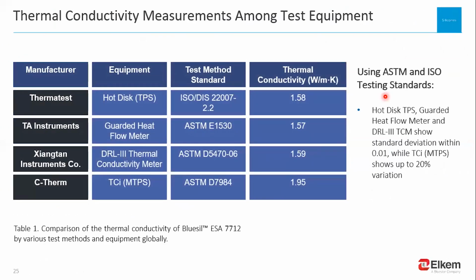In this table, we've summarized the results of all 4 types of equipment used to test one formulation. All results were performed under triplicate testing with the same material while varying test equipment, test method standard, and test engineers at global laboratories. Results from the ThermTest Hot Disk, TA Instruments guarded heat flow meter, and Xiangtan Instruments DRL3 all showed results with a standard deviation of 0.01 watts per meter Kelvin using ASTM and ISO standard testing.